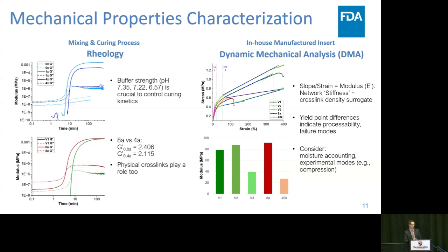And so the yield point also indicates processability, the different ways that you can manufacture it under different temperatures and conditions. And then it's also important here to consider the moisture content, which greatly affects the mechanical properties of the aerogels. And there's different ways of measuring it, including like compression, bending modes. And for these really small inserts, it's oftentimes difficult to do tensile experiments. So it's possible to do different types of mechanical testing.